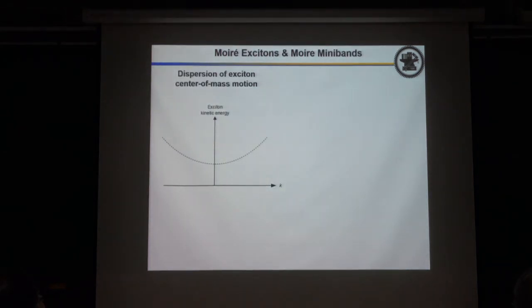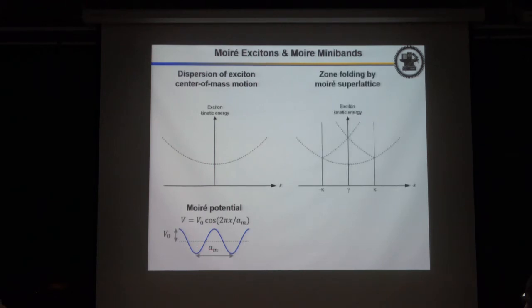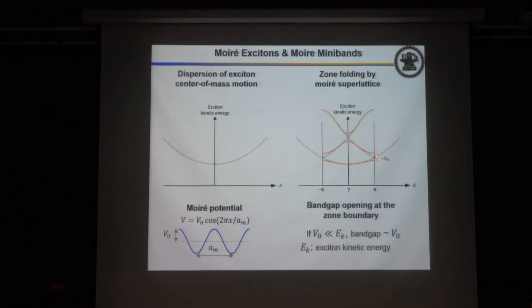Why will the superlattice affect the exciton behavior? For example, this is a dispersion of exciton center of mass motion. This is kinetic energy, and this is the momentum. And if you introduce a Moiré potential here, then you will create so-called zone folding, like you study in Kittel's solid state physics. You can fold back to form this kind of new miniband, and at the zone edge you will form some band gap opening because of Bragg reflection. So if the potential modulation is small compared to the kinetic energy, actually the band gap opening is very close to the potential modulation.